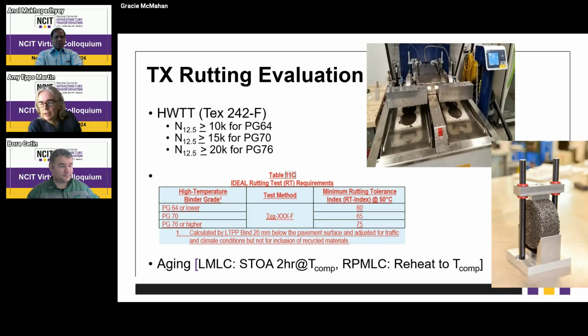In Texas, we're doing the repeated load testing. You see the Hamburg wheel track testing up there at the top, and the ideal RT, which is the simpler test down there on the bottom right. The thresholds are shown there that are in the current BMD spec, and they're based on the PG high temperature grade of the binder, similar to what you saw for New Jersey.